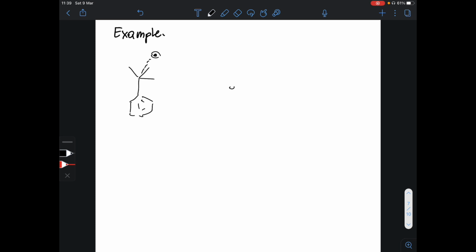So what we are going to see is one carbon atom in the middle and 3 carbon atoms surrounding the middle one. If we refine it anisotropically, we'll probably, if there is some disorder, see that these tert-butyl 3 carbon atoms have ellipsoids that are quite elongated in this plane, which indicates that there might be some disorder.